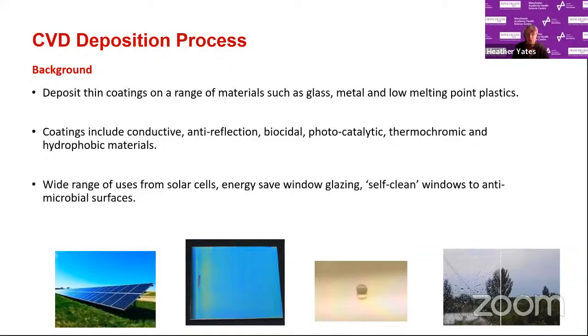So my background is putting thin films on a range of materials, glass, metal, even low melting point plastics. And there's a whole range of functional materials I can produce this way, but the one I'm concentrating on today is the biocidal. Various examples at the bottom of where I've used these coatings. Now the second one along looks like a very blue square of material. It's actually a thin coating of tin oxide on glass, and it only has that vivid blue colour due to the thickness of the film and the interaction with light.